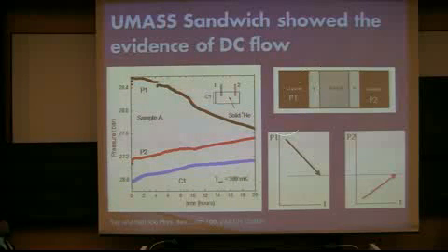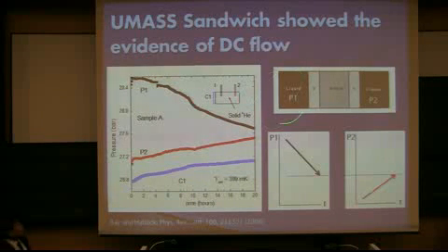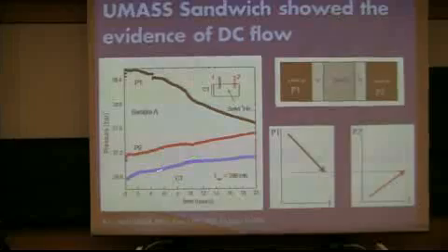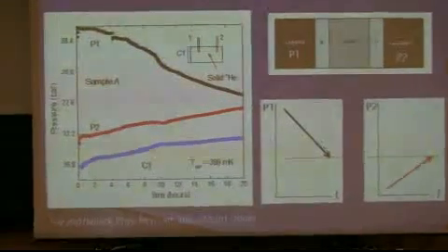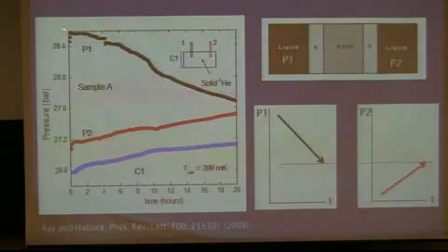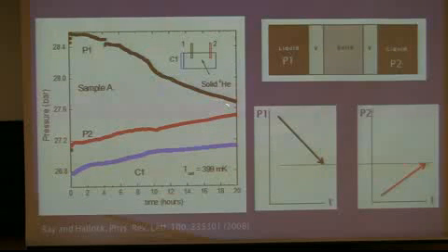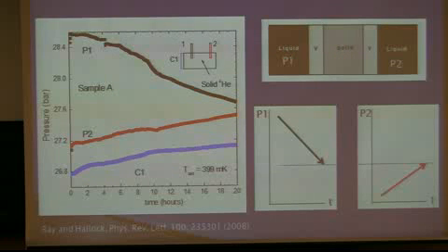Okay, so they add atoms to one chamber, chamber 1. That's why you have a pressure gradient between P2 and P1, right? And as time goes on, the P1 pressure decreases and the P2 pressure increases. So this is a schematic diagram of that previous experiment, and as you can see, there must be a flux through this solid helium. That's why you have an increase in the pressure P2 and a decrease in the pressure P1. And another very interesting observation is that P1, P2 show a linear time dependence.